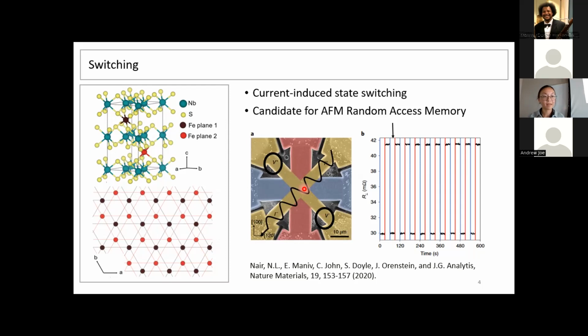Okay. And so we know that this is connected to the magnetism in our material, because if we heat it up to where we're no longer an antiferromagnet, the behavior goes away. If we replace iron with other elements, structurally everything's very similar, but we see very different responses when we do this kind of experiment. But what we aren't able to say just from looking at this response is exactly what we're doing.